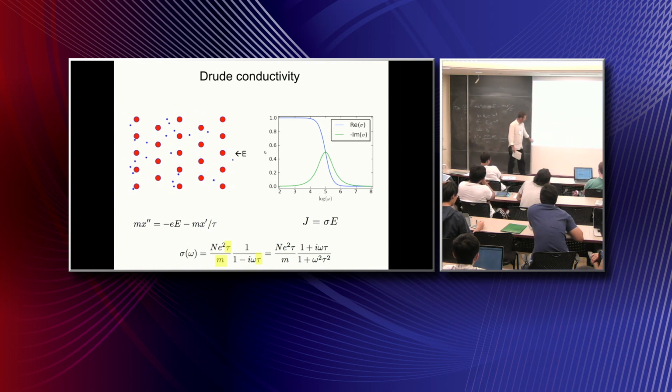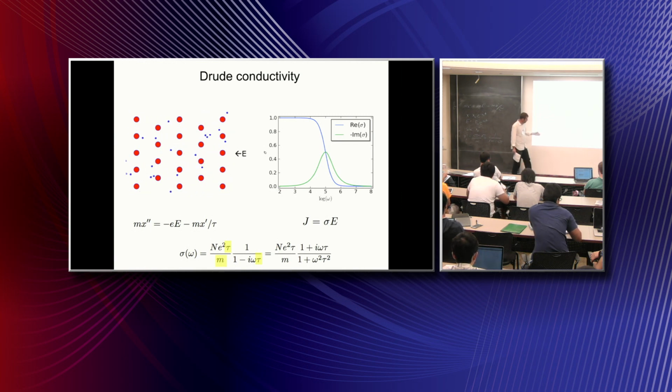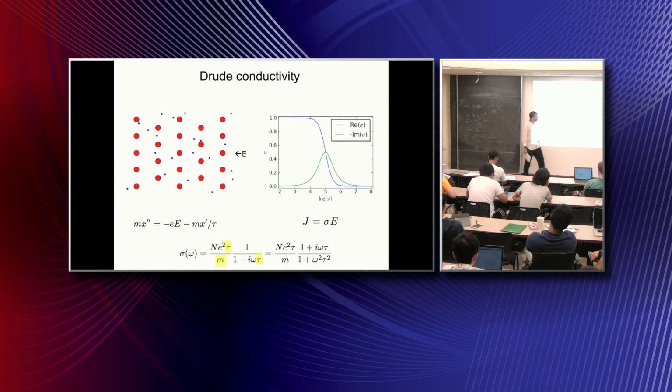One important thing to note is the kinds of physical information that are available here. In principle, if you could imagine measuring the real and imaginary parts of the conductivity, you have access to important material information that otherwise you wouldn't. You can measure tau, the scattering time. If you know the density of carriers, you can find out their mass. You can find this out from the relative size of the real and imaginary parts and from the frequency dependence. And the amazing thing is that